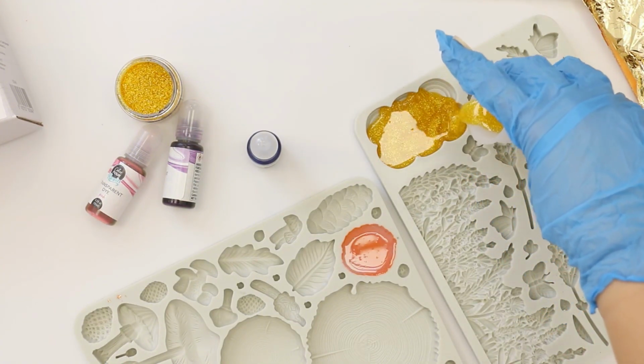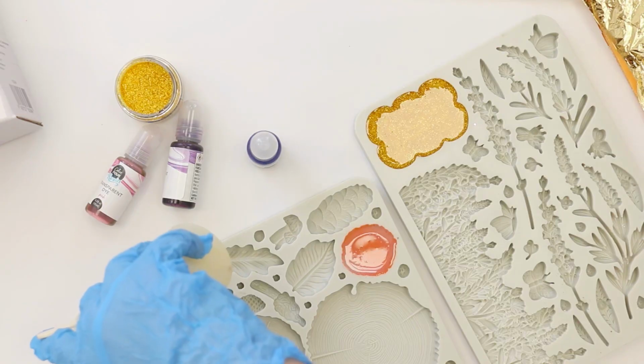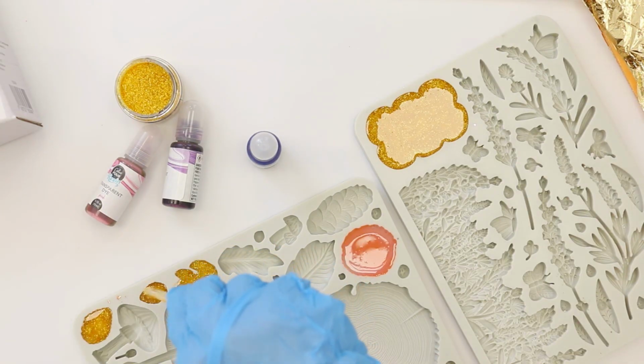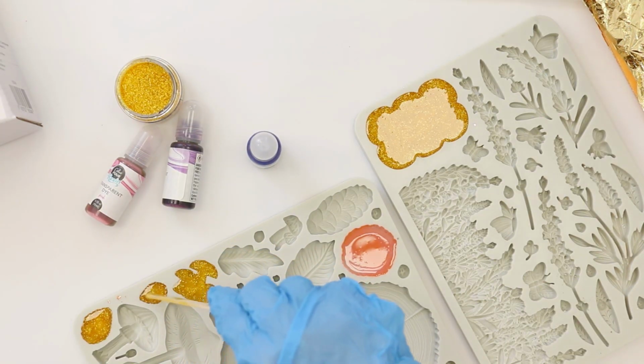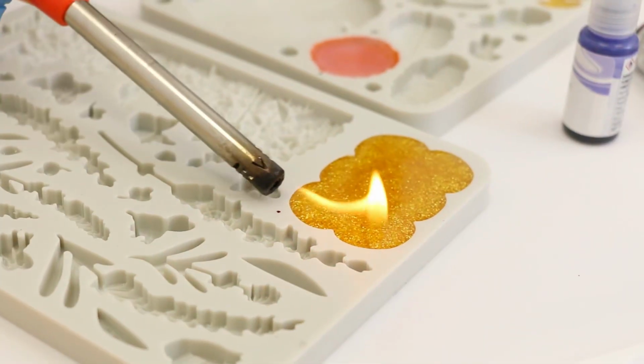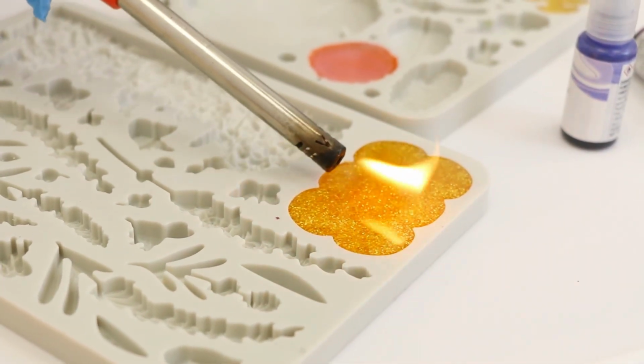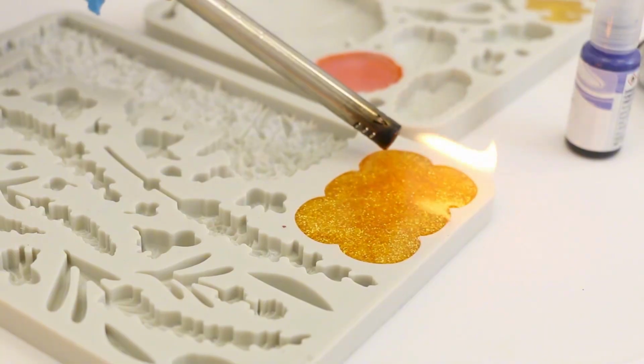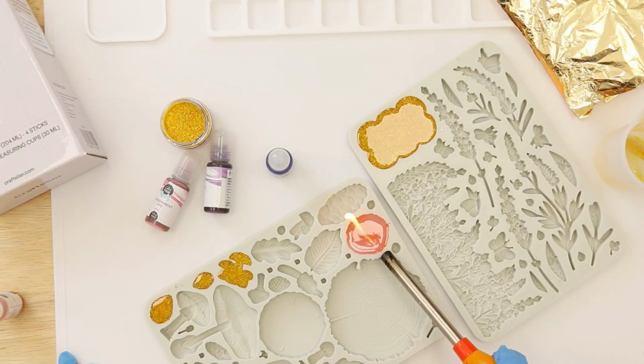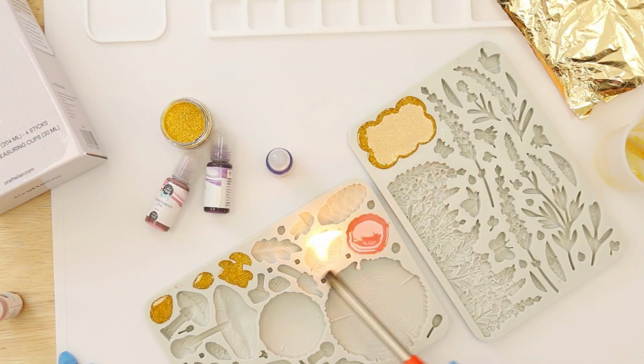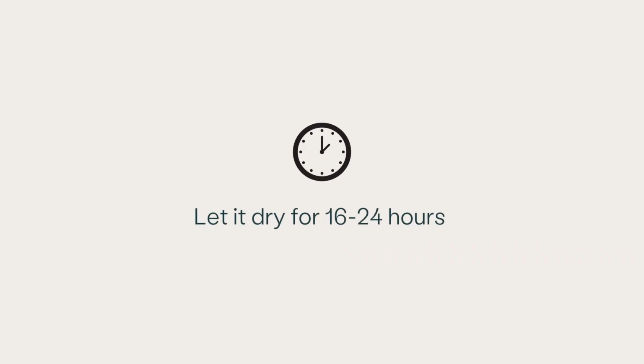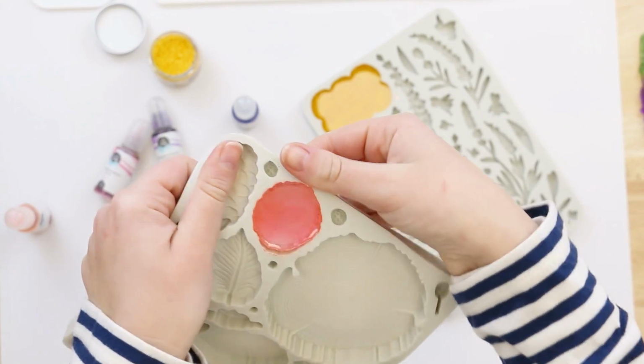Resin tends to shrink a little as it cures, so underfilling may leave sharp edges or indentations that need additional work later. Then use the longer lighter to apply heat and remove bubbles from the surface. Gently pass the flame close to the resin. Repeat this step 4 or 5 times. Now it's time to let it dry for 16 to 24 hours depending on room temperature.